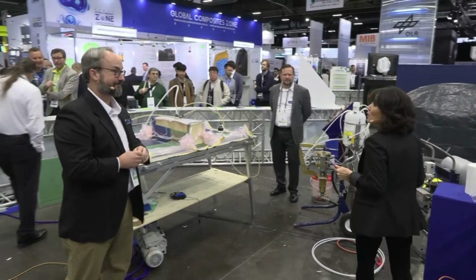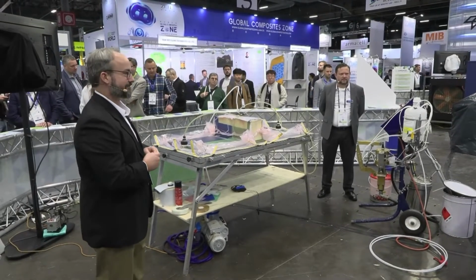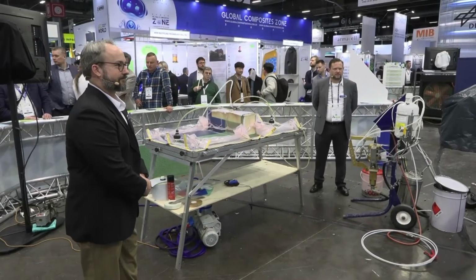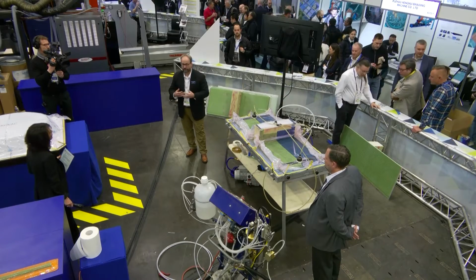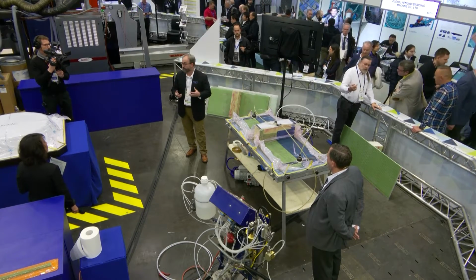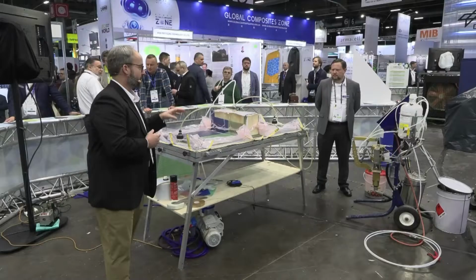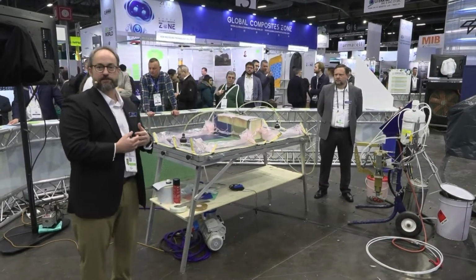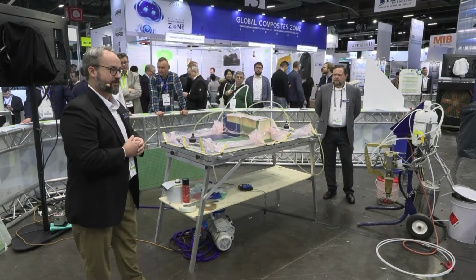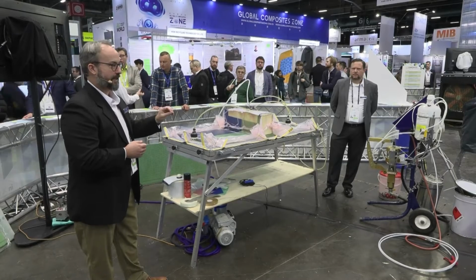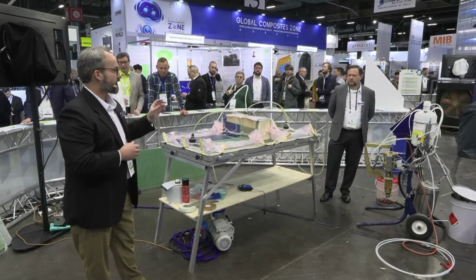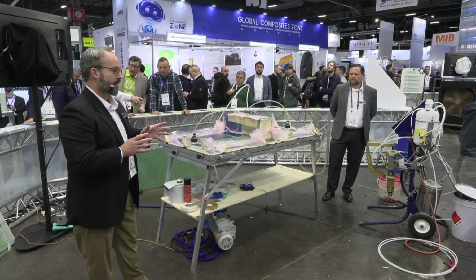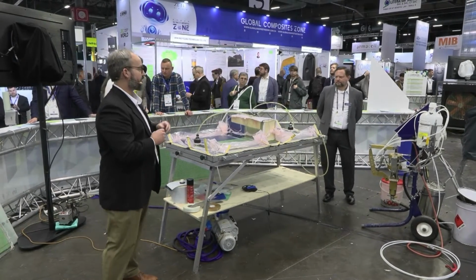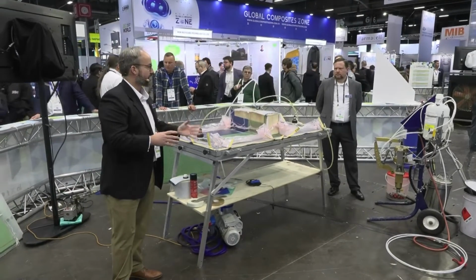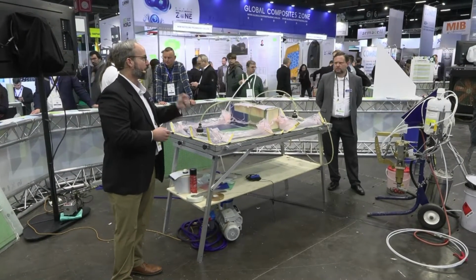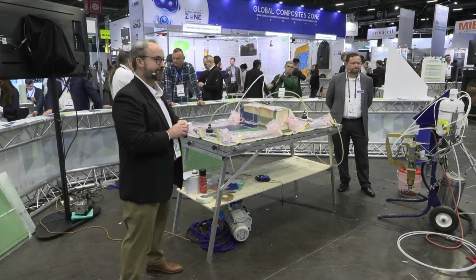Okay, I have a couple of questions for you then, gentlemen. Can you tell me what type of part infusions most benefit from using the VMS3? Yeah, so the VMS3, like we talked about, it's a multi-layer vacuum line that can be placed directly on the laminate. So like the part we're doing here today, it's very good on top of stiffeners, in areas with laminate transitions from very thick laminates to very thin laminates where you get differential flow. If you have trouble spots where you normally get closeouts, you can place the VMS3 in that location, and it will get rid of the closeout, and it won't pull any resin out of the part. Okay, thank you very much.